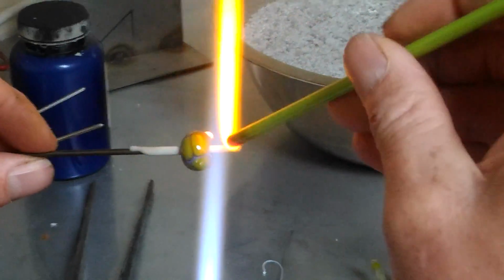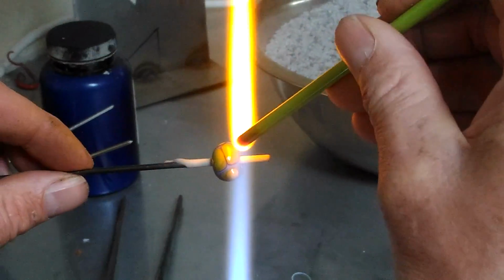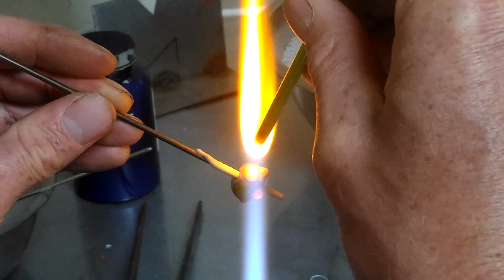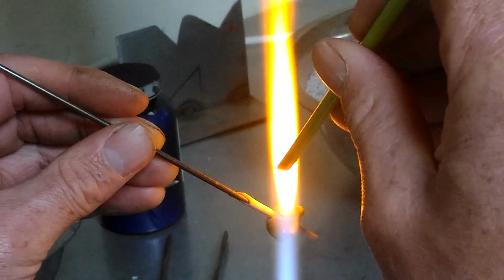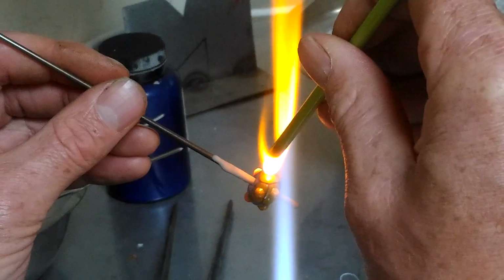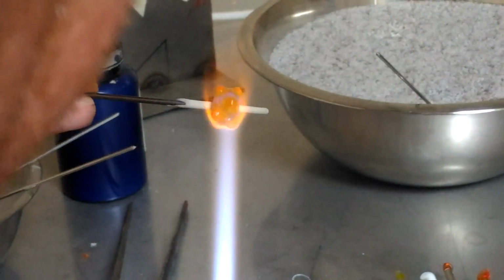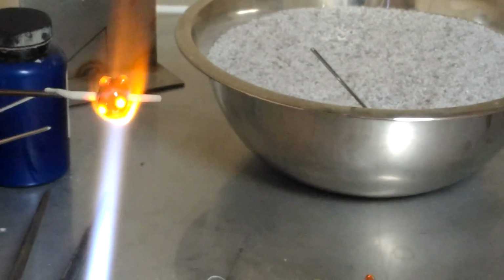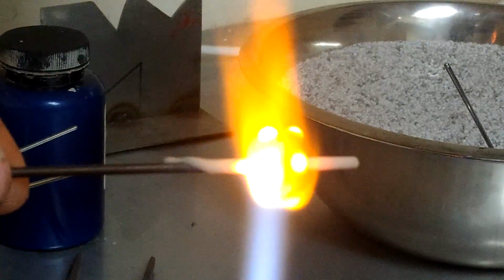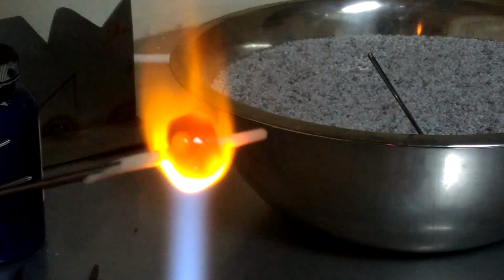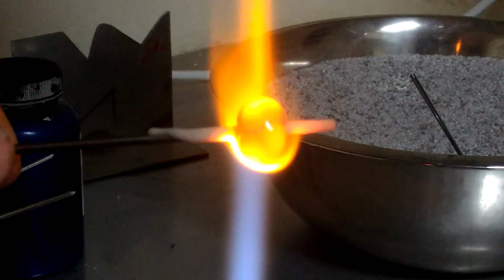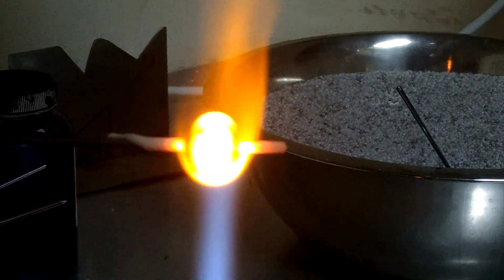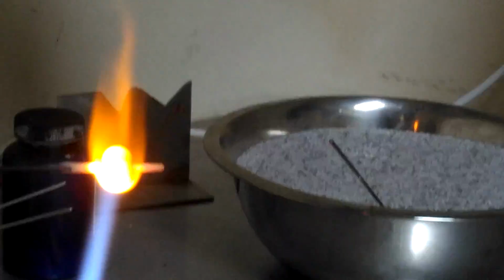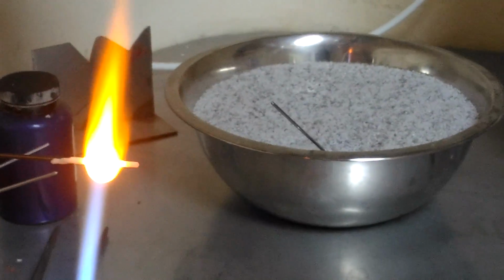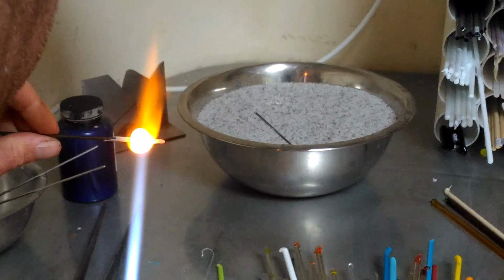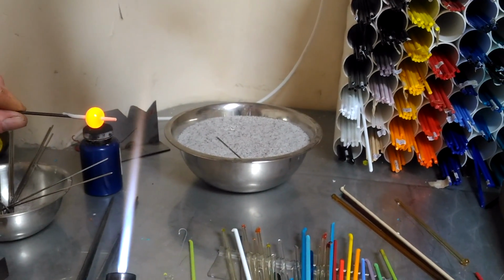And if you take out the oxygen and add more gas, you get a reducing flame which sucks oxygen out of the molecular structure of the glass, and you get a different color. So reduction and oxidization can be beneficial or detrimental. For example, if you want a nice red, but you have too much gas in your flame, the color will reduce into an ugly brown. That's a detrimental effect of reduction. On the other hand, you can get blacks that reduce into a mirror silvered finish, which is very, very nice. So it just depends on how you use the alchemy of the heat mixed with the oxides and the silica, which create the glass.